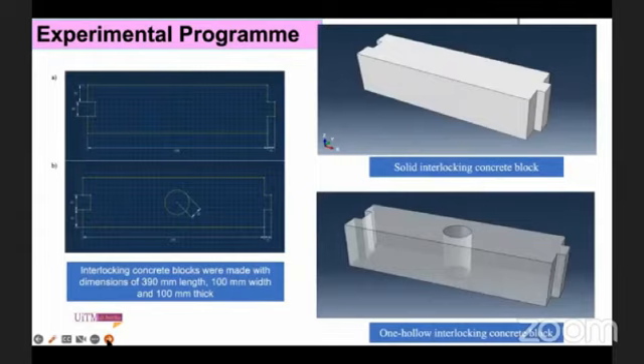So this is the dimension of the interlocking concrete block, with a size of 390 millimeter length, 100 millimeter width, and 100 millimeter thickness. The width of the groove is 30 millimeter, and the tongue is also 30 millimeter. The depth of the groove is 15 millimeter, the length of the tongue is 15 millimeter, and the hollow is located at the center of the interlocking block. This one is the 3D view of the solid interlocking concrete block, and this one is the 3D view of the one hollow interlocking concrete block.